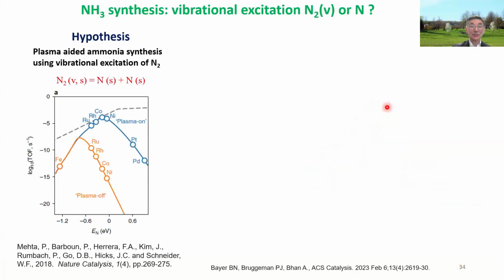Around a few years ago, around 2018, Professor Bill Schneider at Notre Dame published a paper in Nature Catalysis. It really excited a lot of people. This figure basically shows the catalytic reactivity. The horizontal axis shows the adsorption dissociation energy volcano curve as a function of the bond energy. The yellow shows the thermal catalysis, and the green shows plasma catalysis. Once you turn on plasma, vibrational excitation of nitrogen, the reactivity increases by several orders of magnitude.